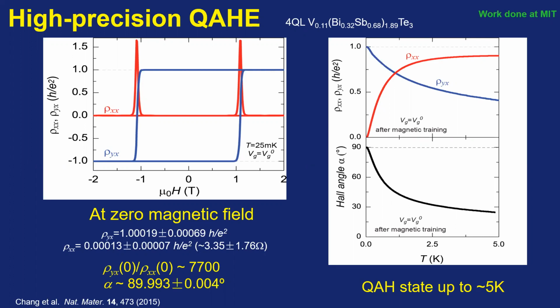antimony telluride, we can see the Hall resistance quantized. At zero field, the longitudinal resistance is just 3 ohm. So the Hall angle is very close to 90 degrees. And this kind of very high precision quantum anomalous Hall effect is further confirmed by the temperature dependence of longitudinal resistance, Hall resistance, and Hall angle. For the temperature dependence of longitudinal resistance, it shows a continuous dip below 5 Kelvin. So in this sample, the quantum anomalous Hall effect can survive up to 5 Kelvin.